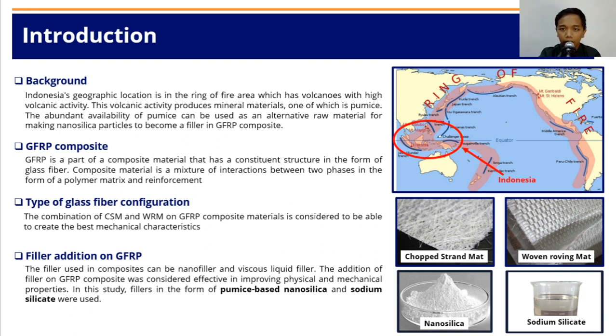Several studies have proven that composite with unsaturated polyester resin composition reinforced with woven roving mat glass fiber shows good strength, whereas the composite with a chopped strand mat reinforcement has a good flexural strength. So the combination of a chopped strand mat and woven roving mat on glass fiber reinforced polymer composite material is considered to be able to create the best mechanical characteristic.